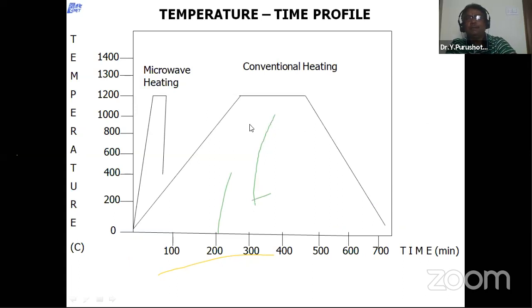You can see here the temperature-time profile. In microwave heating, if the set temperature is 1200, you can reach 1200 within minutes only. Whereas in conventional heating, it will take hours to reach 1200. Then we have to hold for 3 to 4 hours, and only then the desired density or properties will be obtained. And again, to bring it back to room temperature will take a few hours.